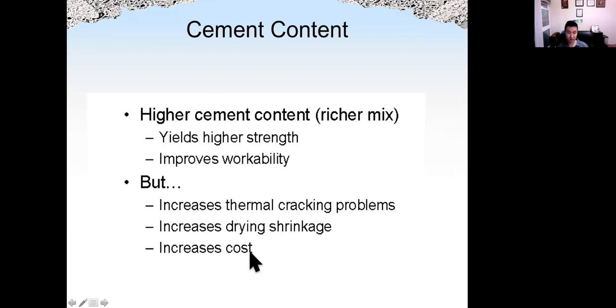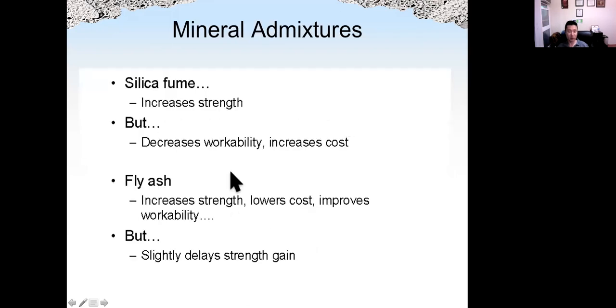higher. For mineral admixtures, silica fume will increase the strength. Cost will be much higher. Silica fume is 10 times more expensive than cement. Workability will also be lower because the particle size is small. For fly ash, it will increase the strength, reduce the cost, improve the workability, but delay the strength gaining speed. If you want higher early age strength, you cannot use fly ash.